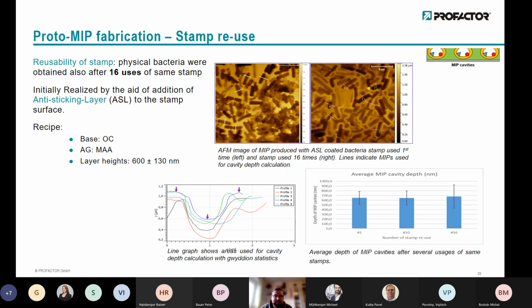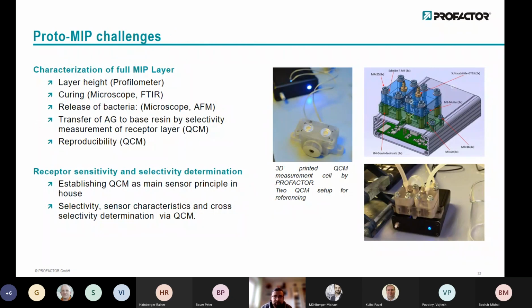However, here a so-called anti-sticking layer was used, and therefore we more or less blocked the chemical information transfer, unfortunately, which we found out quite late. Nevertheless, we adapted and optimized by not using such an anti-sticking layer, but tuning with the anchor groups and so on, and with the process itself. We also updated our own QCM measurement setup, which is quite tiny and uses two QCMs, one for measurement and the other as reference, containing just a non-imprinted polymer.